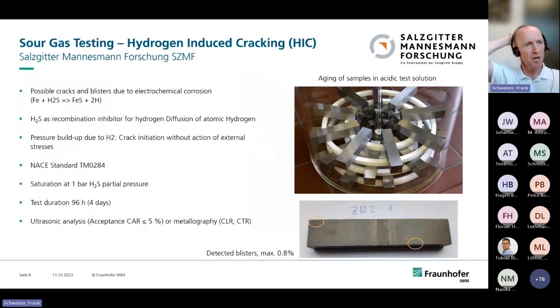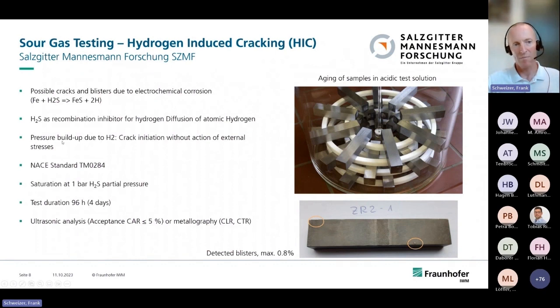At Salzgitter-Mannesmann Forschung, there was sour gas testing, which was very important. They looked for hydrogen-induced cracking. You take different samples of weld material and of sound material, and you put that into 1 bar H2S partial pressure and test that for 4 days. There could be a pressure buildup due to hydrogen, and then you have blisters, what you see in the lower picture. That's common for ferritic steels. So you have an acceptance rate, which has to be below 5%. And what we found in the project for the X56 steel is that the detected blisters are a maximum of 0.8%. So this fitted well for the hydrogen caverns.